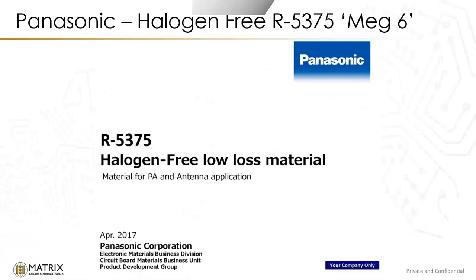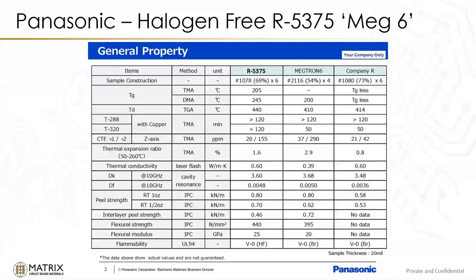So the R5375, the much awaited, highly anticipated halogen-free Megtron 6, is available in a test case right now, so limited quantity, limited testing that we have going on, but we've seen some very encouraging properties with the Meg 6. In particular, of course, it's got a high TG, which makes it more robust. It's got a very, very high TD, so we're encouraged with that, very stable in the thermal performance. And the one I wanted to point out too is that I'm used to seeing Meg 6 and Meg 7 with high T288s, but on this particular chart we've introduced the T320, so an even more stringent test, and it performs very well. So those are very good properties.